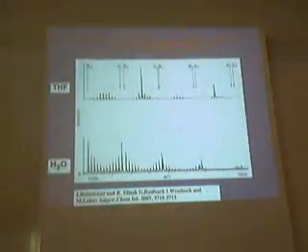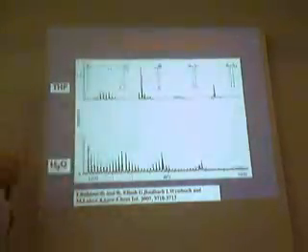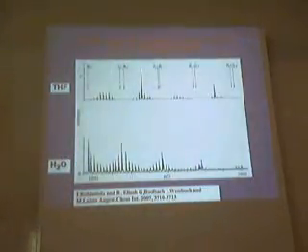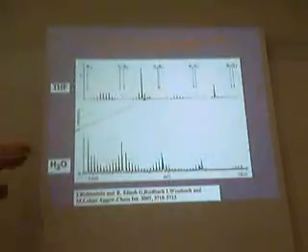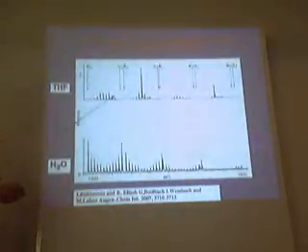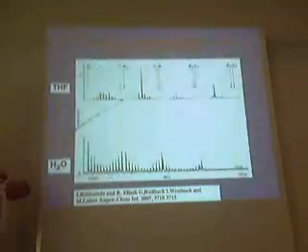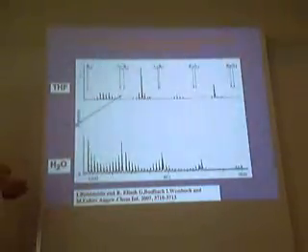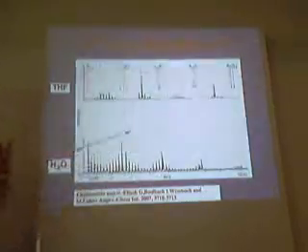But they were interested in the synthesis of peptides, and therefore their reactions were performed in organic solvent. By repeating the conditions of their reaction in THF, what we found is that they form heterochiral peptides, a binomial distribution in a certain sense.